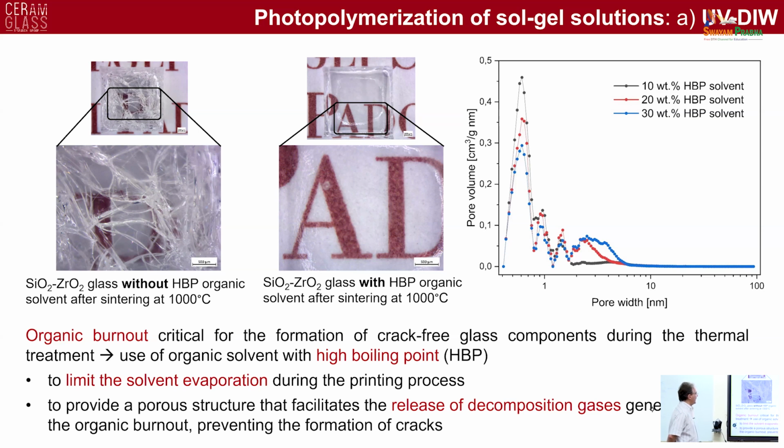glass. And we monitored the presence of nanopores or mesopores inside the material due to the introduction of the high boiling point solvent. And you can see that indeed we were able to introduce these pores inside the part, which helped with the organic burnout.